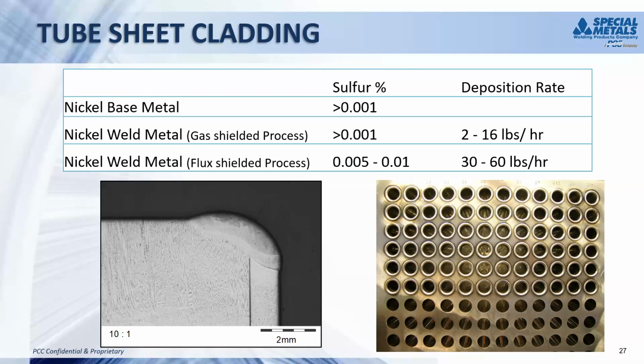However, you do run into the problem of picking up some of that sulfur from some of the other flux-based components. The reason that's a particular problem with a tube sheet is, as you see in the picture on the left, when they're welding these tubes up, you essentially already have a notch or a crack built into the joint design. So you really need very low sulfur so you avoid a solidification crack running right up into the weld, where you already had a predetermined notch. Next slide.